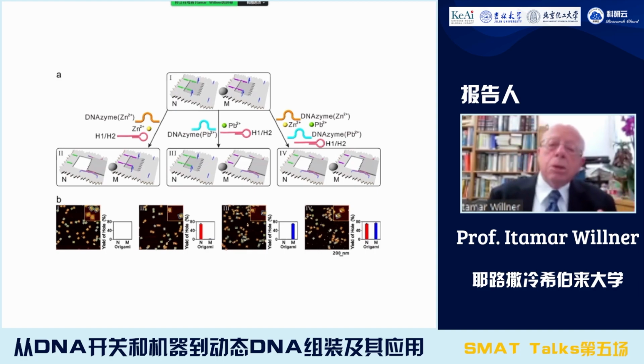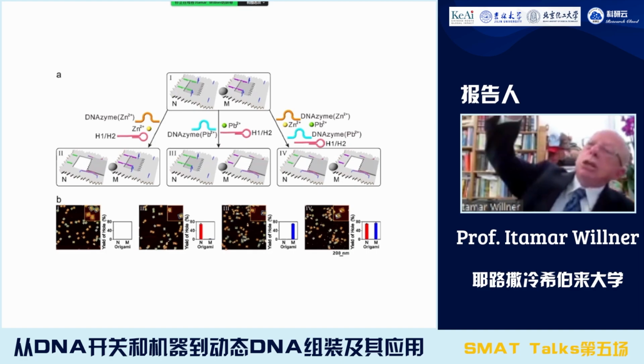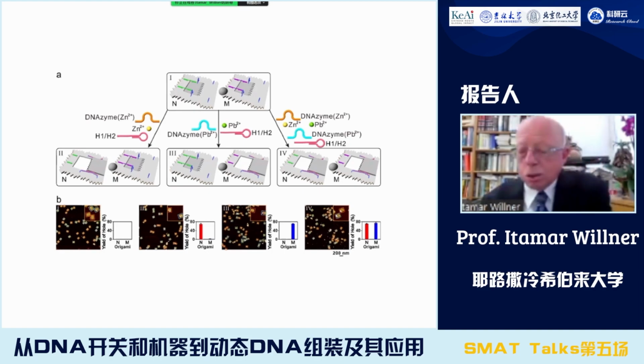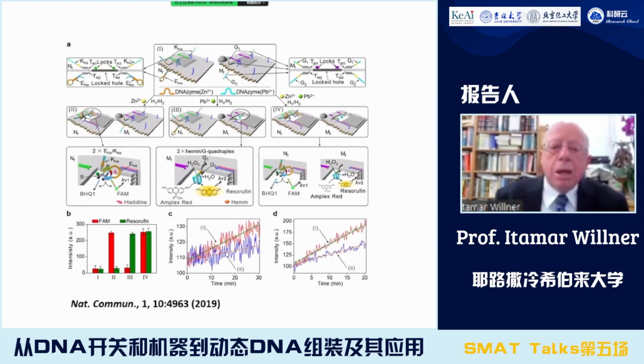What we can do is we can now engineer from the beginning, on opposite sides of the open hole, tethers that, when we unlock the window, will be subunits of a DNAzyme, and in the confined hole, we will generate either a zinc-dependent DNAzyme or a hemin G-quadruplex-dependent DNAzyme,